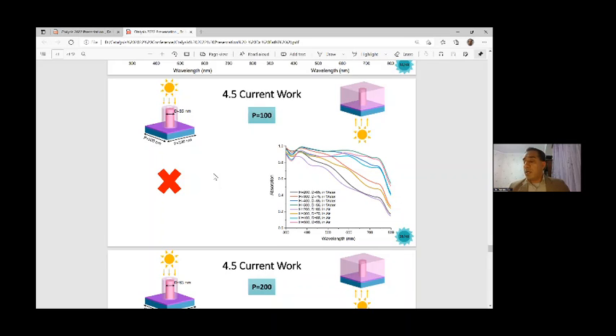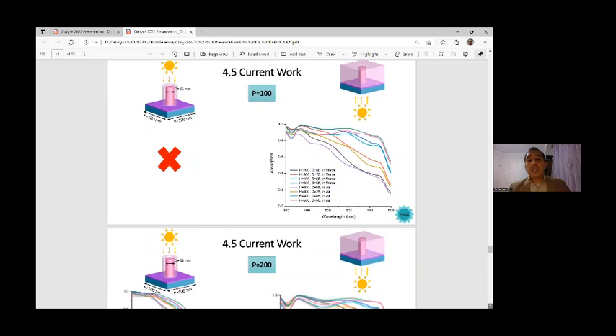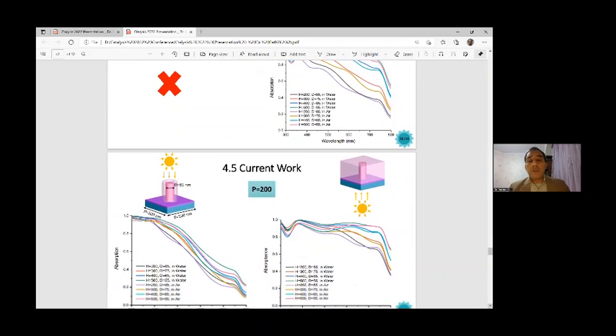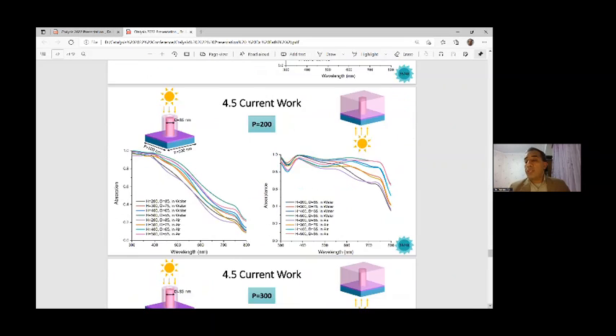So in this slide, for the value of P equal to 100 nanometers, only structure 3 has been simulated and the curve is presented. For P equal to 200, in this slide you can see a comparison between two structures: structure 2, where the sunlight is from above the structure, and structure 3, as I mentioned, from below the structure.